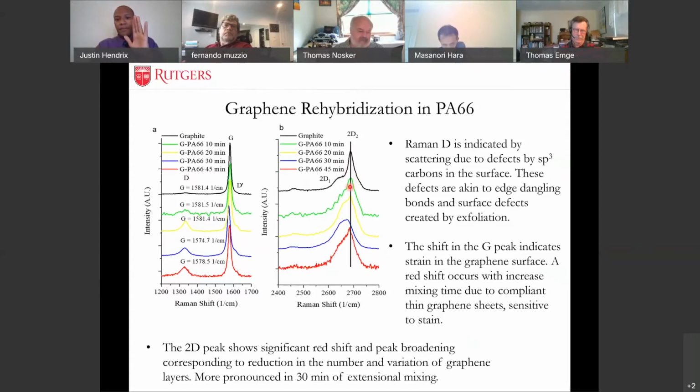That splitting of those four modes says that we're getting a plurality of graphene within the surface, given by the Raman work. So it speaks to the fact that we have many-layer and also few-layer graphene within the material. This is another clue that's seen from the TEM results.